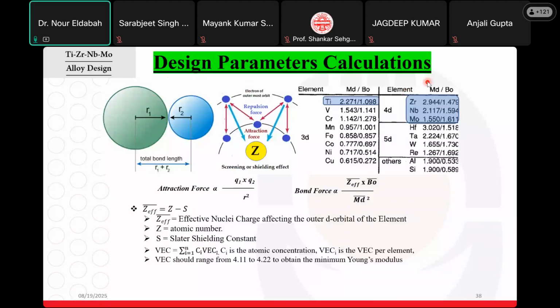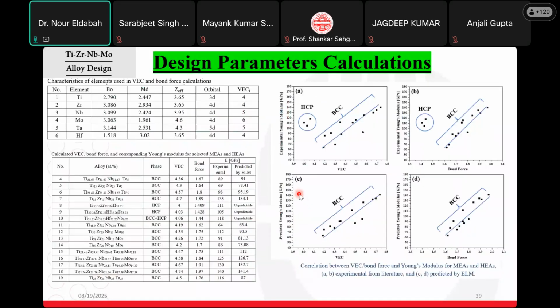We depended on the design parameter calculation for the valence electron concentration and the bond force between the constituent elements inside our alloys. We calculated this bond force and studied the relation here, the experimental value to the valence electron concentration and the corresponding bond force and the constituent phase. For most widely used high entropy, medium entropy, or traditional titanium alloys in this table, we plot the relation between the elastic modulus and bond force and valence electron concentration, and we could find that lowering the bond force in a BCC phase and lowering valence electron concentration in BCC phase will ensure low elastic modulus.